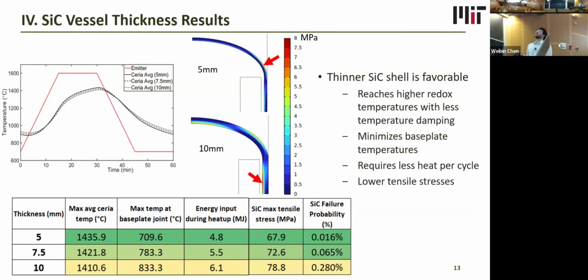As for our mechanical results, we can see that when we go thicker, we actually end up increasing the maximum tensile stress and the failure probability. And interestingly, the position also changes to a different spot. While this might seem a little bit surprising at first, it can be attributed to the fact that the stresses here are dominated by thermal expansion. So making a component thicker will not always help you in terms of mechanical stress.